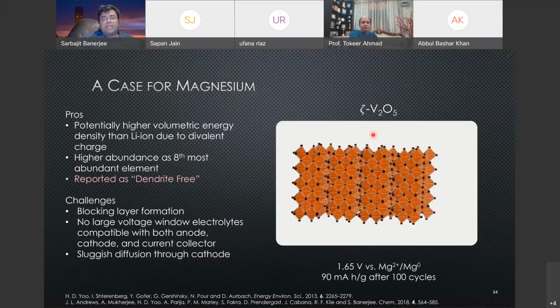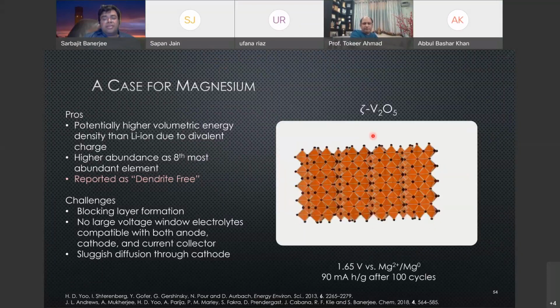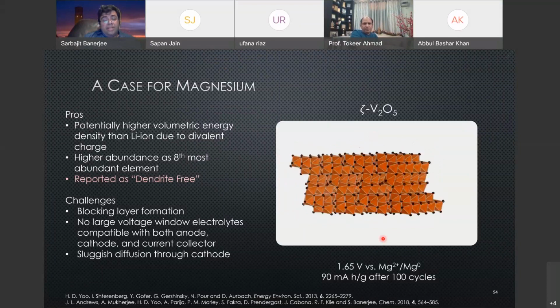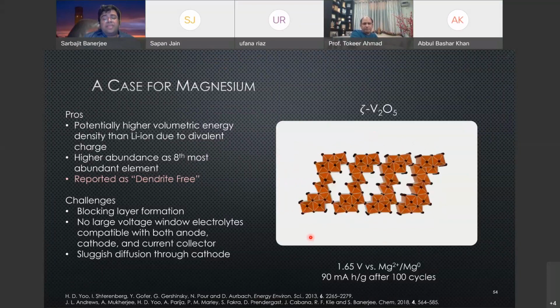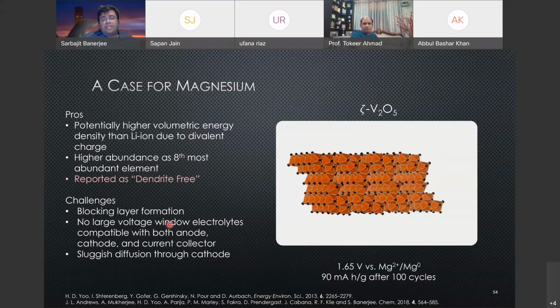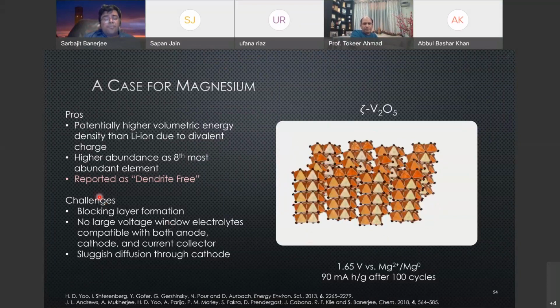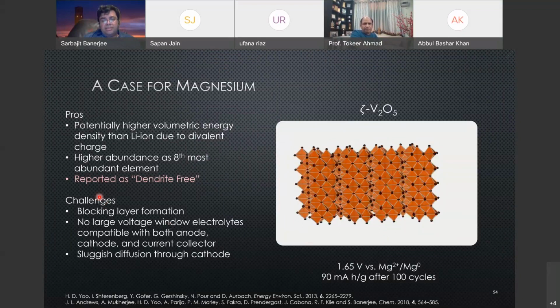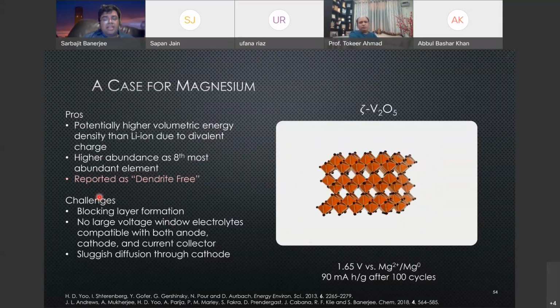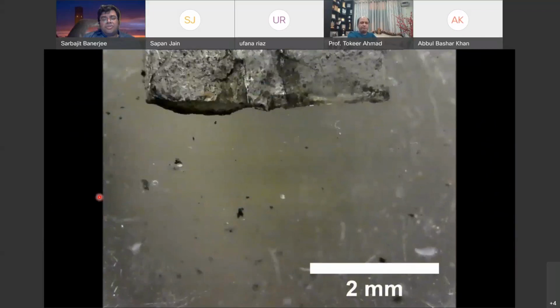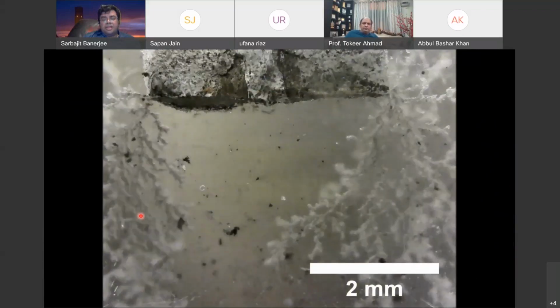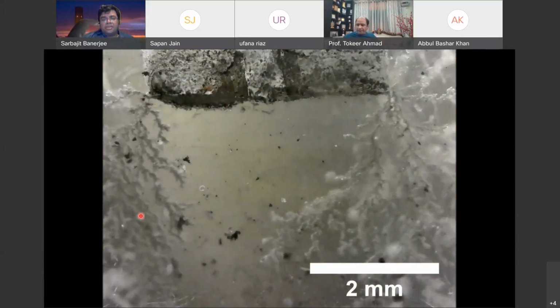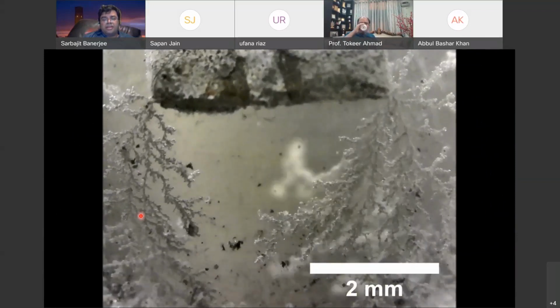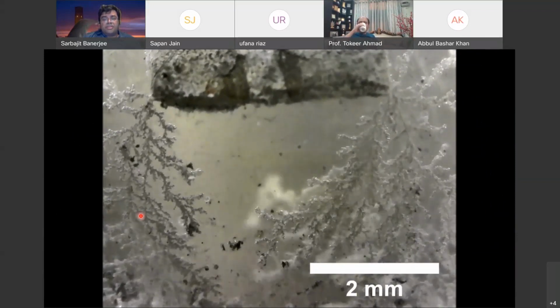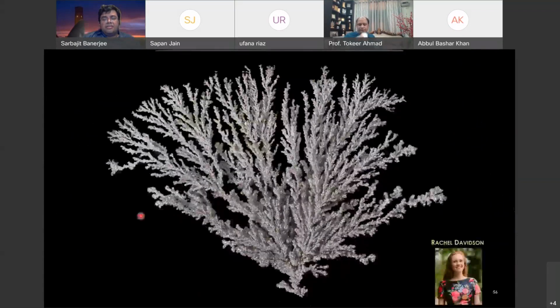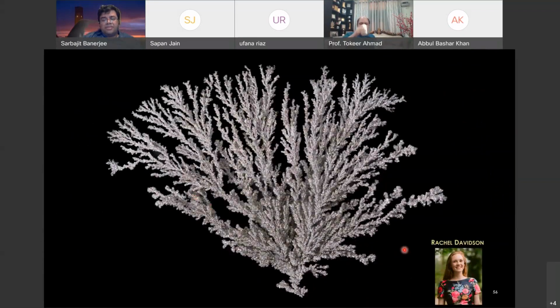But part of the story here is the idea that we were very excited that we have a good magnesium cathode, and we wanted to use a magnesium metal anode, because there were some claims that this is dendrite free. It's probably true that magnesium is less likely to form dendrites, but let me show you some data that actually shows that magnesium does also form dendrites. So you can see this here very dramatically. Dendrite formation is still proceeding, especially at the edges. And here's an example. This is work by Rachel Davidson.